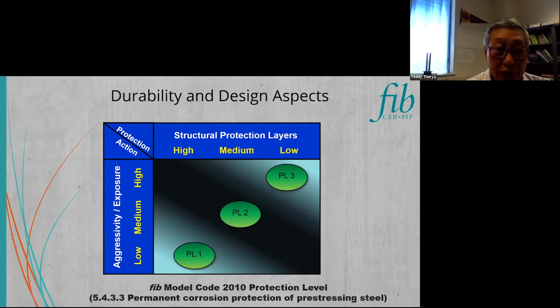After the workshop, FIB have created a model. What type of corrosion protection? They depend on the structural protection layers and aggressivity and exposure to environment. So there's protection and action. For example, if you have very low structural protection and you are in a very high aggressive environment, you really need PL3 protection level. If you have very high structural protection layers and very low exposure, what you need is only PL1. So what kind of protection? Each of the owner and consultant that design this bridge have to make sure that they follow the national code, whatever the protection the national code requires.